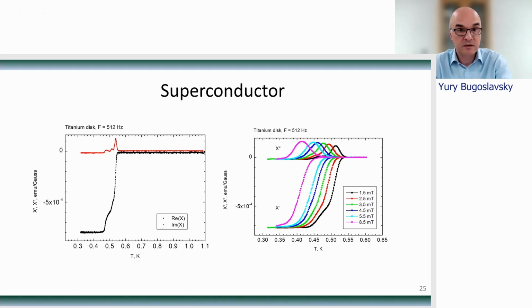Very good method for phase characterization of the material. Further, if we apply external DC magnetic field by switching on our superconducting magnet, and that is the picture on the left, we can see that the transition is pushed down to lower temperatures. And again, noting the position of these peaks in chi double prime, we can very conveniently build the phase diagram of the superconducting material.